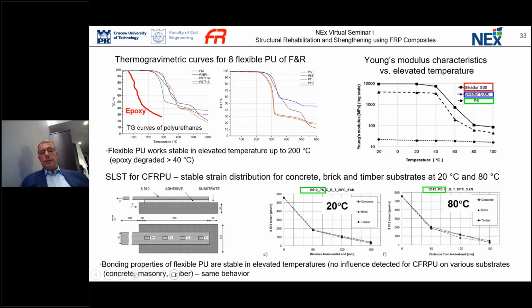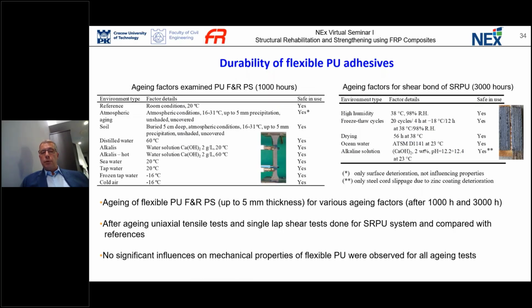If we compare this single lap shear test at two temperatures, room temperature and elevated temperature, the system where we bond the composite material with polyurethanes to three kinds of substrates, I mean concrete, brick, and timber, you can compare that on the same scale, practically the behavior is the same, so there is no difference in behavior if we apply elevated temperatures.